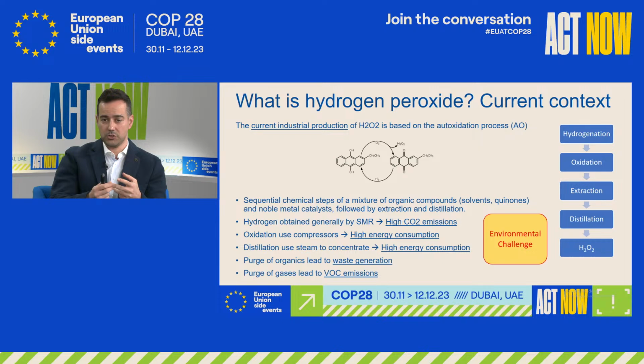Where do we get the hydrogen? It is generally through steam methane reforming. And that technology generates a high amount of CO2. For the oxidation, we generally use air, and this requires a high energy consumption in the compressors. It's the same for distillation. To increase the purity of the material, we use basically steam. That requires energy. And because we use organics in our loop, we need to purge those materials, and therefore there are also VOC emissions. So altogether, even though the process is a very old process, 70 years old, and very well improved, it represents an environmental challenge.